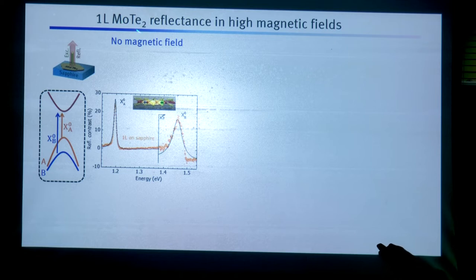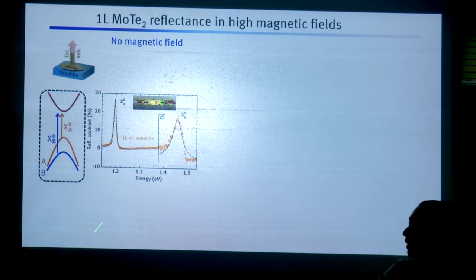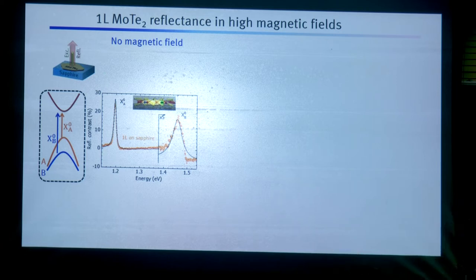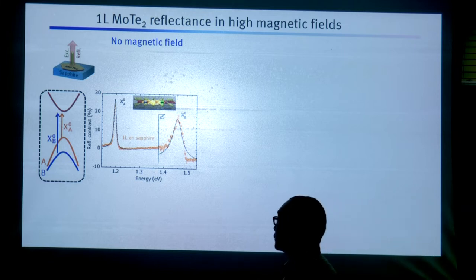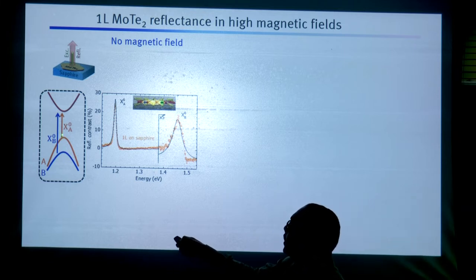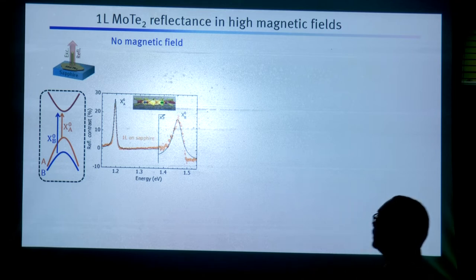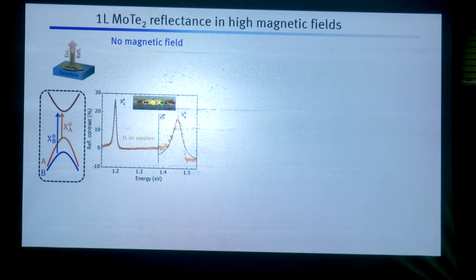Let's take a material which is molybdenum ditelluride. Again, a single layer. This has two excitons visible in this material around the infrared region of energy, because there are two kinds of bands. So one transition is there and one is there. So what we are checking is the reflectance spectrum. So this is energy and this is reflectance.